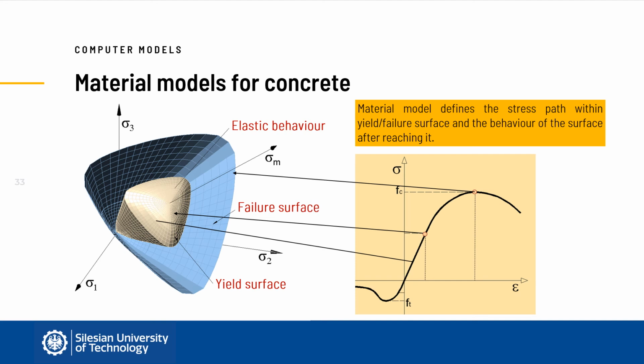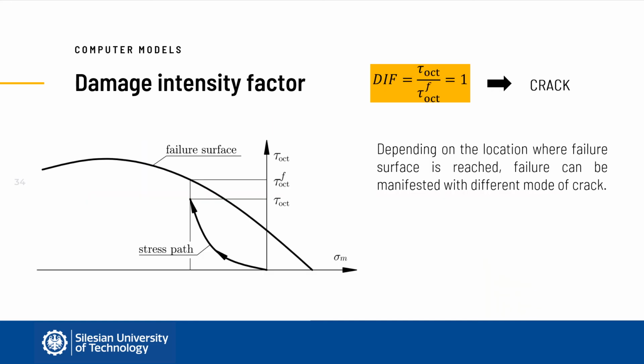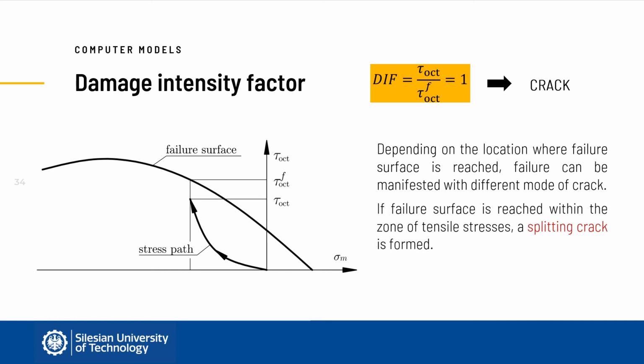The descending branch of the stress strain diagram represents the behavior of the failure surface after fracture, which in this case would be progressing degradation of concrete until total failure. Depending on the location where the failure surface is reached, fracture is manifested with different modes of crack. If the failure surface is reached within the zone of tensile stresses, a splitting crack is formed. Such a case can be simplified to a one-dimensional damage analysis. In case concrete fails under compression or any complex stress state, the crack mode can be different.